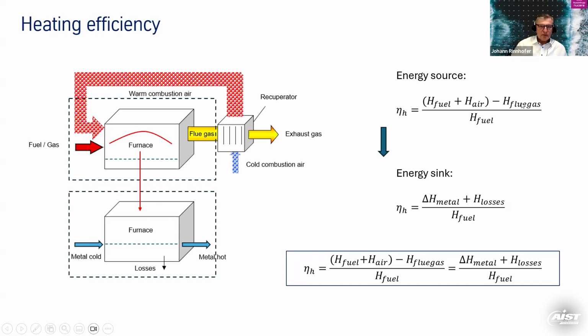And if we relate this to the energy coming in with the fuel, we have this heating efficiency. So the difference between the incoming energies and the outgoing energies, when you look at the gas only, is sort of useful. These energies go into the metal and also the losses of the furnace in the end. So we can say the thermal efficiency or heating efficiency of this furnace you can describe by the difference of the gases coming in and coming out, the energy of those gases, and they are covering the metal and the losses, the heat of the metal and the losses in the end.